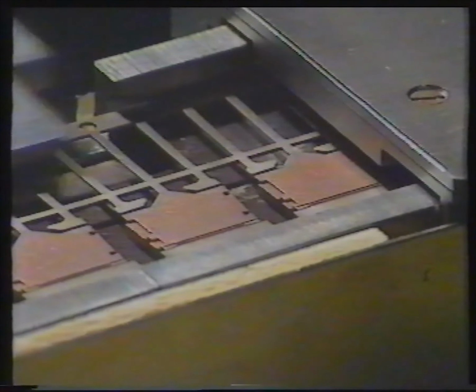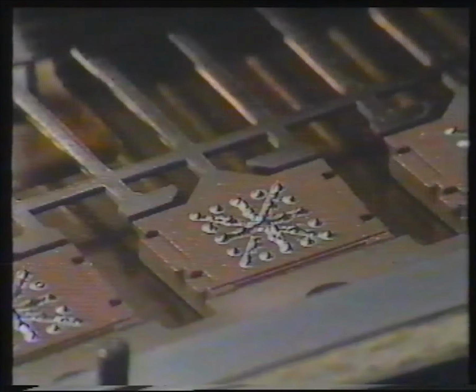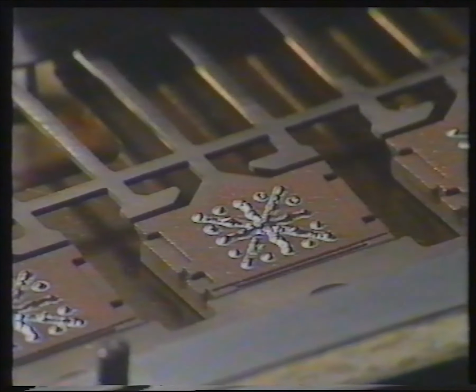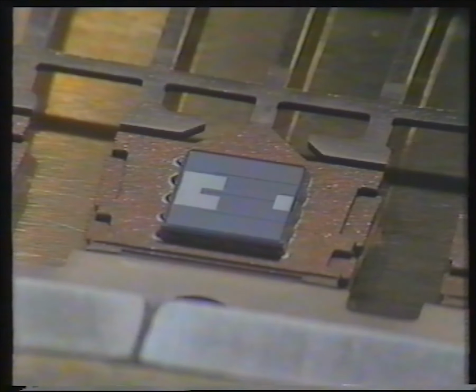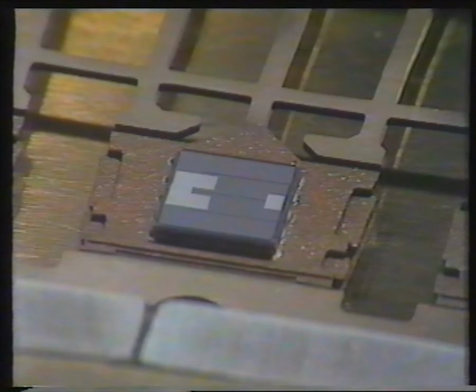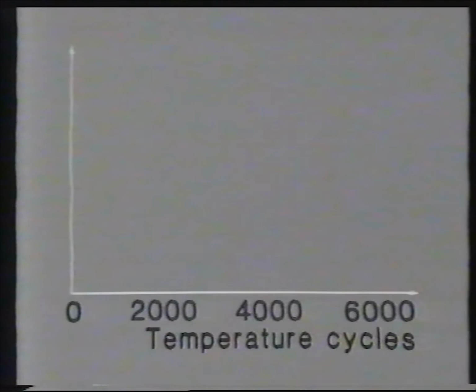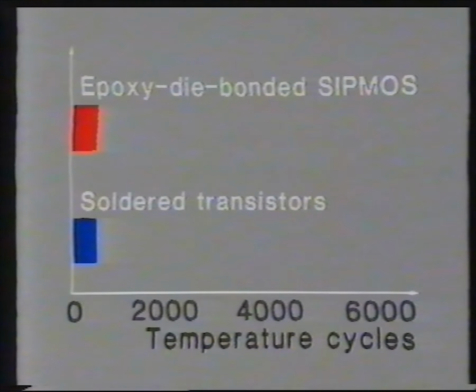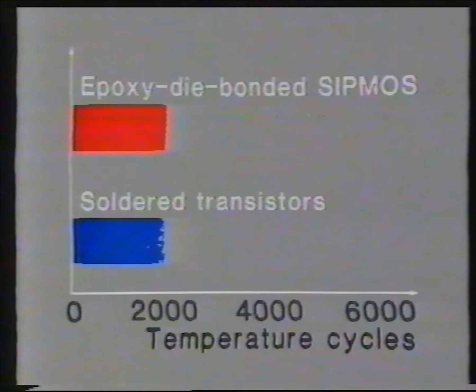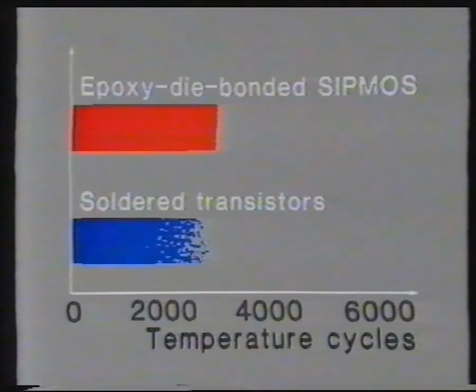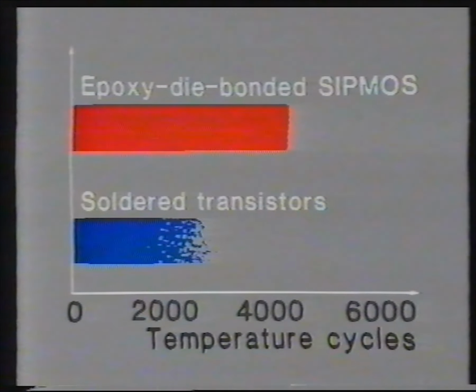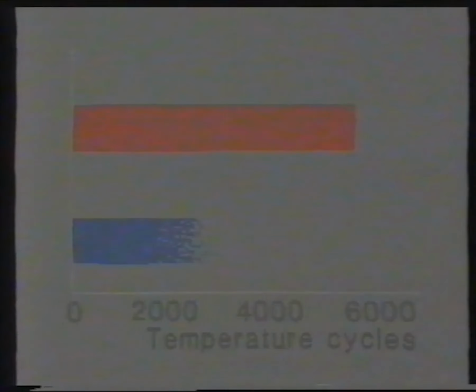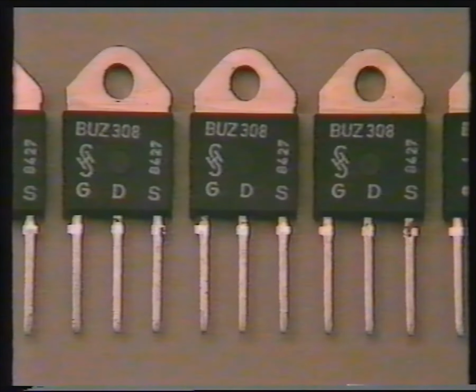There is a lot of technological know-how in SIPMOS. A further example. SIPMOS chips are not soldered to the housing, they are epoxy die bonded. The result? Much better temperature cycling stability and increased reliability. Whereas soldered transistors totally failed after only 2,000 to 3,000 temperature cycles in a test, SIPMOS transistors were still functioning without problems after 5,000 cycles. SIPMOS, the leading technology under the surface.